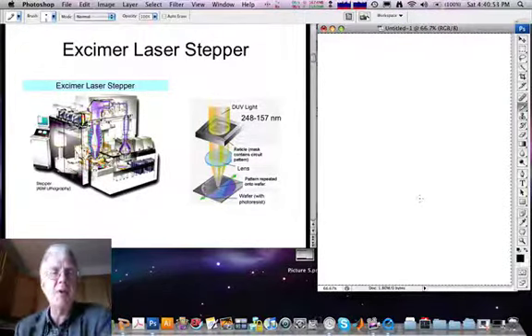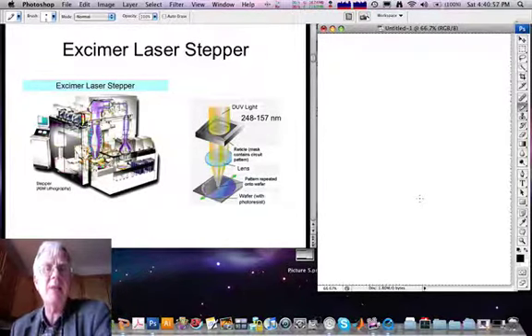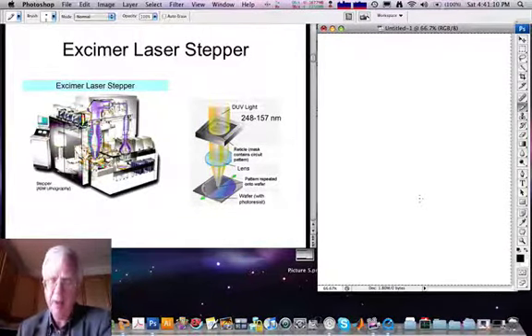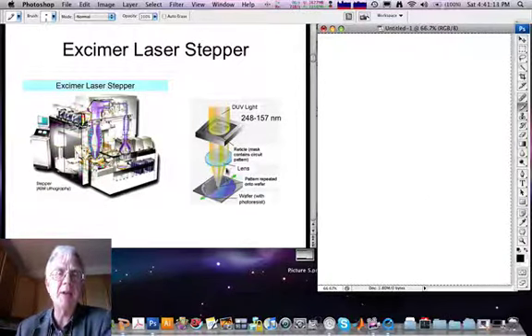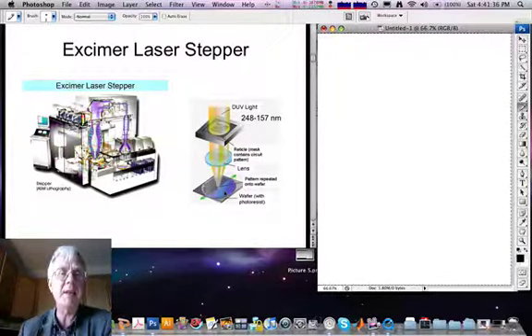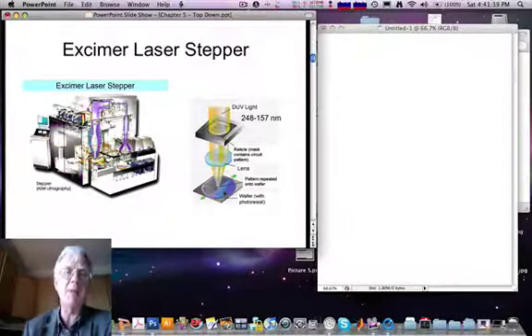One way to do this is to use a very short wavelength, and excimer lasers can provide wavelengths down into the range of somewhat over 100 nanometers. This means that with a high numerical aperture lens, features as small as 50 nanometers or so can be etched. One of the limitations is that a lens for focusing light down to such small features doesn't have significant range on the surface before it goes out of focus, and so for that reason a very specialized lens will be used together with a stepper that moves the device so the pattern can be exposed repeatedly over the surface without the need for wide field optics.